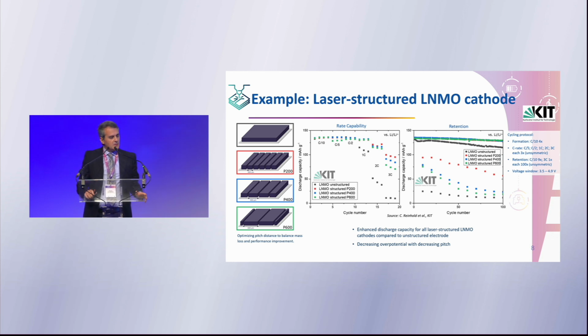Given the results that we got on the laser-structured LNMO cathode, we have also investigated different types of structuring. Focusing on the linear structuring, we have investigated structuring the electrode with different distances, what we call here P factor. We have investigated the unstructured reference against structured at 200 micrometers between the different linear carvings, 400 micrometers, 600 micrometers, and we have found an optimum around 200 micrometers for this specific technology. And you can see how P200, as we call it in this slide, provides us the best performance, and this best performance is particularly visible when we look at a very high C rate, so 5C.